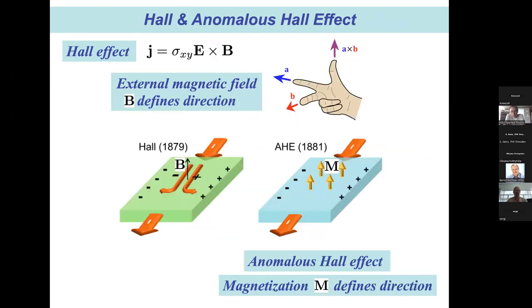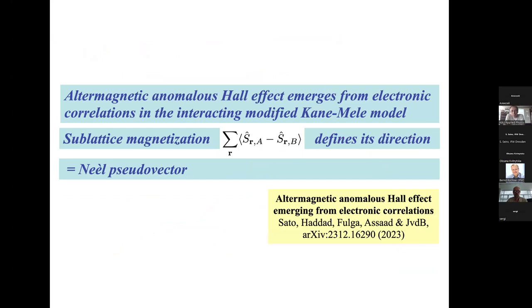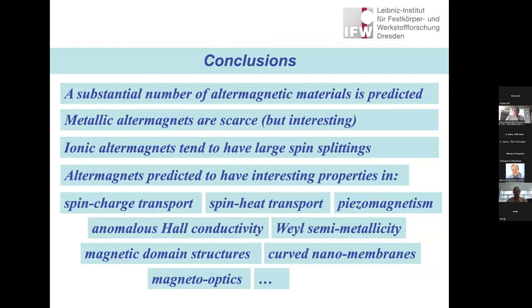I will not talk about the anomalous Hall effect, which I really like, however. We have a very nice paper out there. I'll just go to the conclusions now. So the conclusion is we have a substantial number of altermagnetic materials, at least 60. Metallic altermagnets are scarce, but interesting because they have these spin currents you can get there. Ionic altermagnets tend to have large spin splittings. Altermagnets have been predicted to have interesting properties in spin charge transport, as I mentioned. I did not mention spin heat transport, which is also something we're working on. Piezomagnetism, anomalous Hall conductivity, we're also working on that.